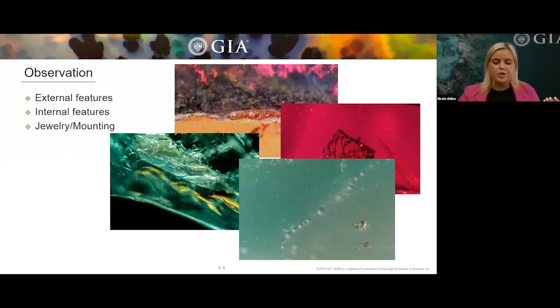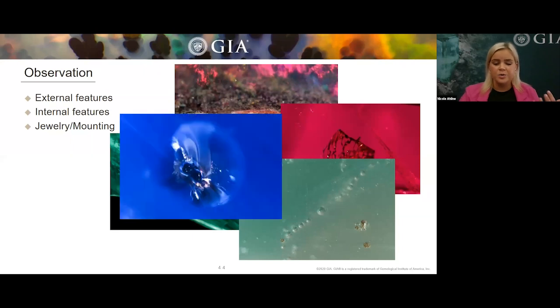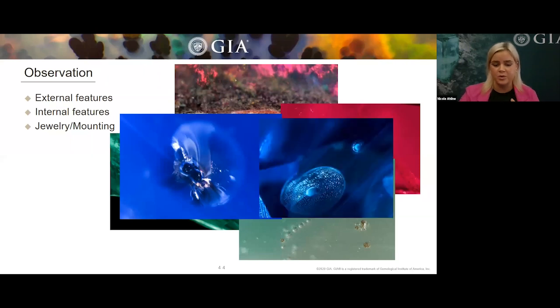They will also look at the inclusions present and the nature of them. So if the stone has potential to be heated, are the inclusions still intact? So here we see unaltered zircon crystals and they don't show evidence of heat. However, if zircon is heated, this is what they will look like. And we call these snowball crystals. So you can see it has this white frosted appearance around it once heated, but prior to being heated, you have sharp grain boundaries on these black crystals. Again, we're going to be looking at how the inclusions interact with the stone. Are they higher or lower relief than the host stone?